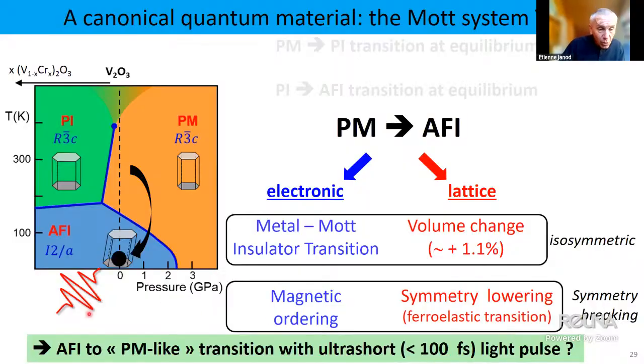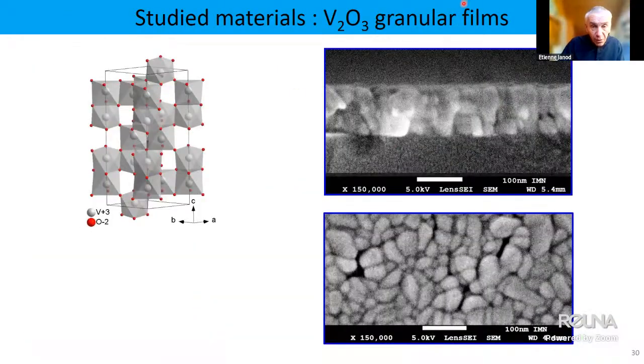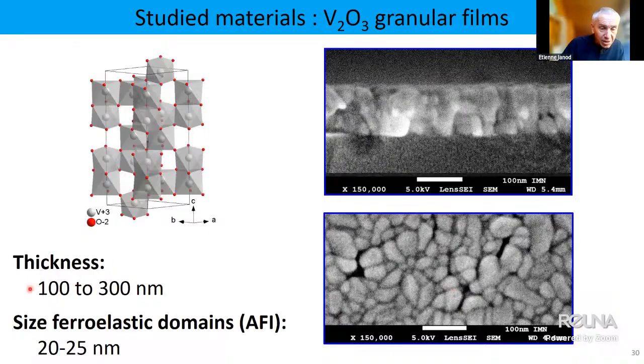Okay, so what we study is whether, if we are in this low temperature phase, we can induce a transition from this antiferromagnetic insulating state to something which is metallic-like. We have studied granular films that I already showed you, and their typical thickness was a few hundred nanometers. But what you have to keep in mind is that the ferroelastic domains, that is domains that appear inside of the grain, are in the 20 to 25 nanometer range.